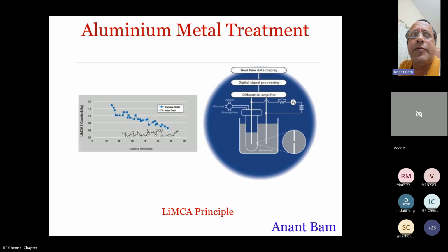Once some small particle of oxide momentarily passes through that orifice, that oxide, which is an insulator, takes away the area of conductor from that orifice.